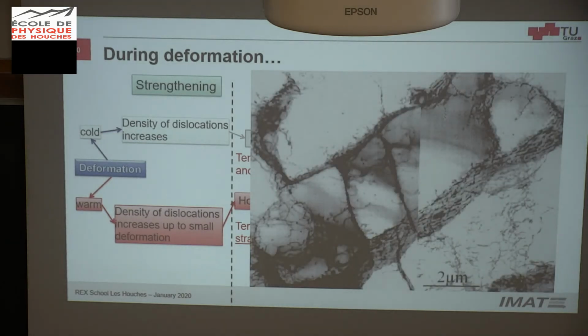But basically, we are speaking about materials that during cold deformation form cells. So they don't form stacking faults, they don't form twins. These cells look like this. So we have the dislocations at the cell walls and spare dislocations within the cells. And during high temperature deformation, the cell walls get sharpened, and then you have subgrain formation instead of cells.